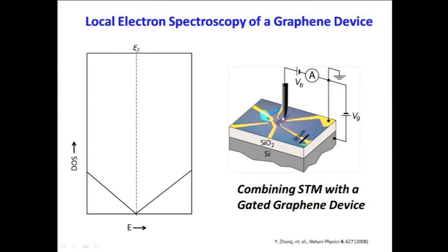And what we expected to see when we did this experiment a few years ago is a V in the local density of states, in the dI/dV, because the local density of states of a material often mimics the total density of states, which is linear for graphene. And there's the Dirac point. And so that's what we expected to see. But when we did the experiment, that's not what we saw. In fact, we saw something that looked kind of different.